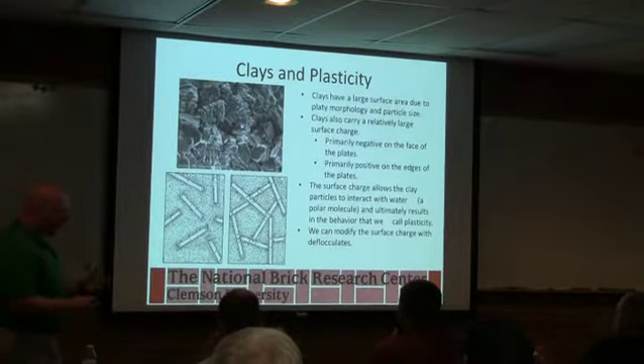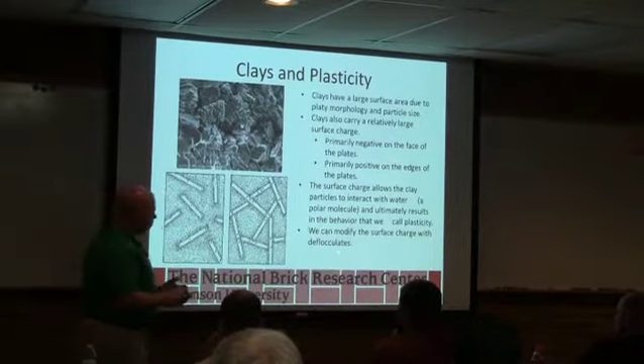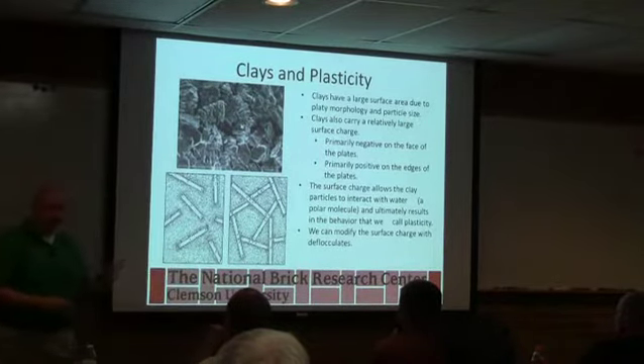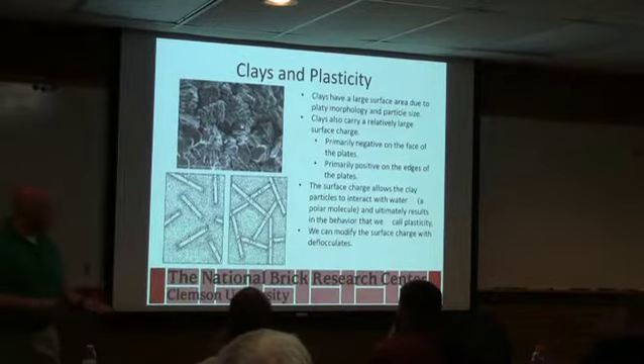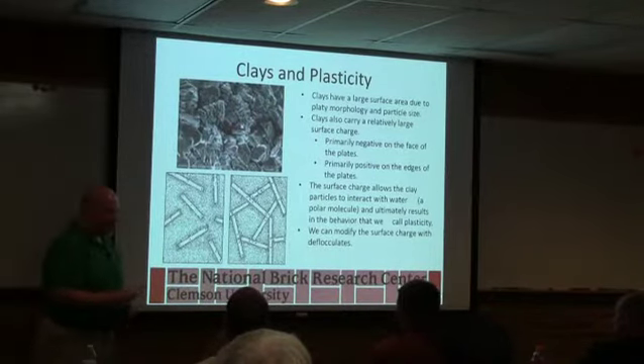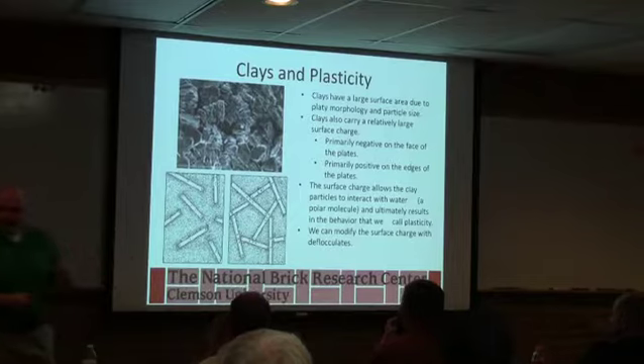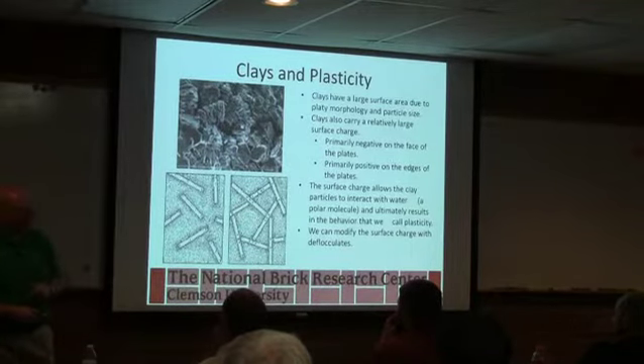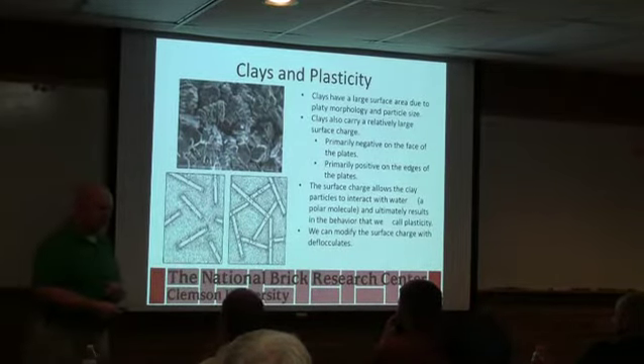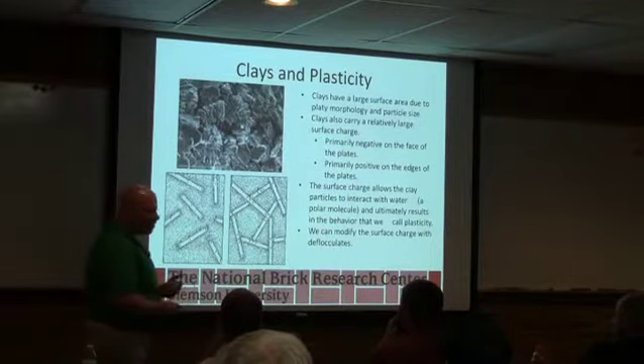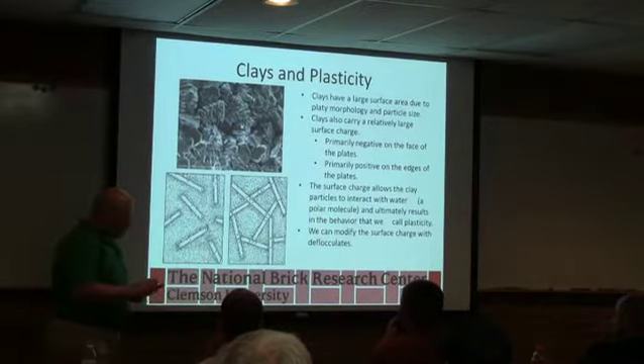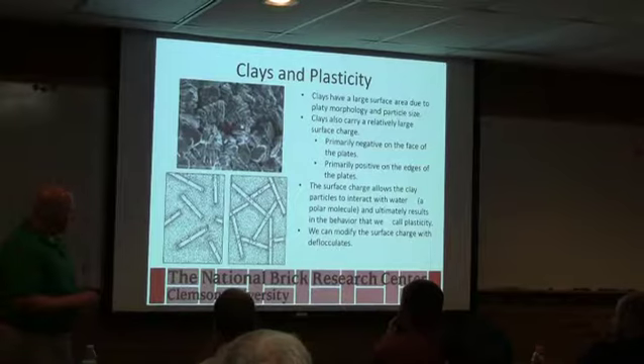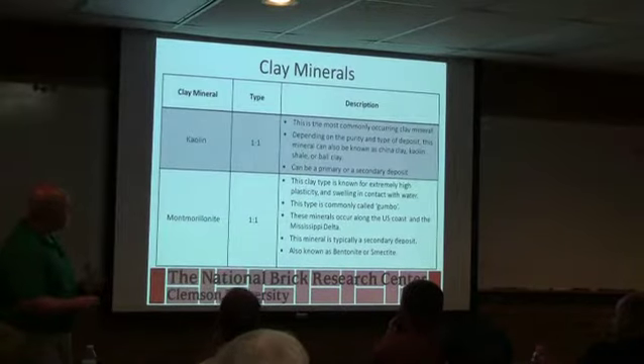If we have a very high clay content, we might need to use a deflocculant. Like, anybody ever use soda ash? Okay, soda ash is a deflocculant. You're modifying that surface structure, and usually when you add something like that, you get more plasticity with less water, right? You don't have to add as much as before. And that changes the way the material behaves, usually for a good thing.